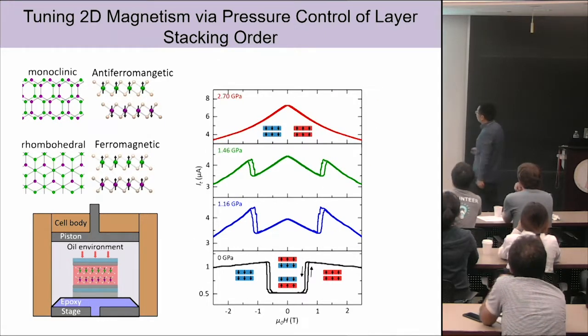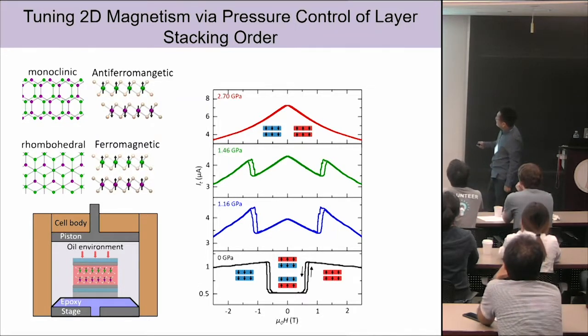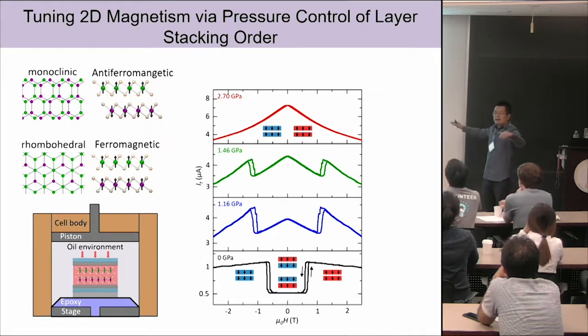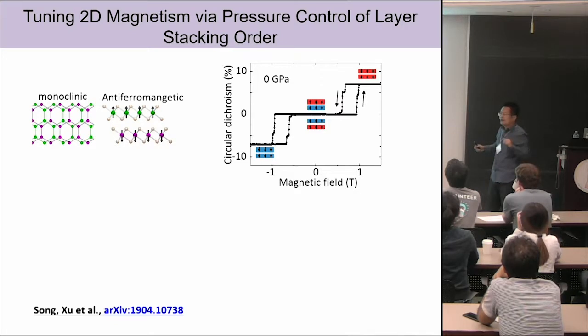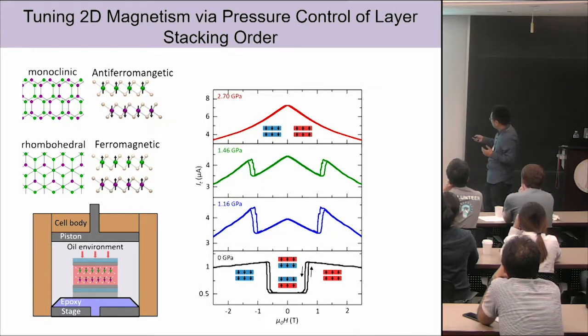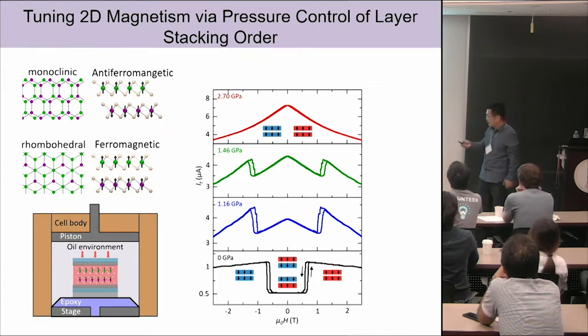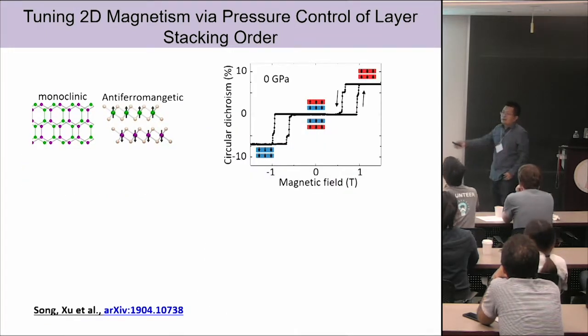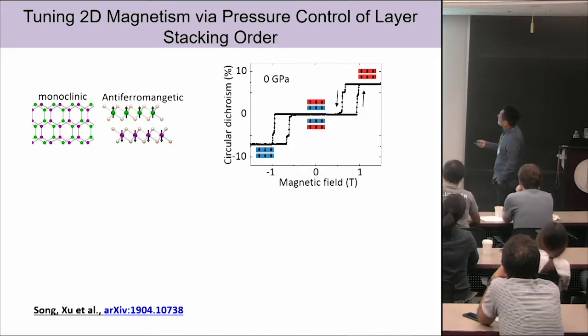As we keep increasing the pressure, what we see is that this sharp spin flip transition actually vanishes at the highest pressures. What we see is only this kind of sloped magnetoresistance. This is coming from the graphene contact, okay? But the spin flip transition has disappeared. What this indicates is, well, maybe the antiferromagnetic state has already transitioned into a ferromagnetic state, right? To confirm that, we take the sample out, then we perform magneto-optical Kerr rotation measurements. And here, just to remind you, for a pristine bilayer in the monoclinic structure, we do see the vanishing of this Kerr rotation signal. So we do have antiferromagnetism.